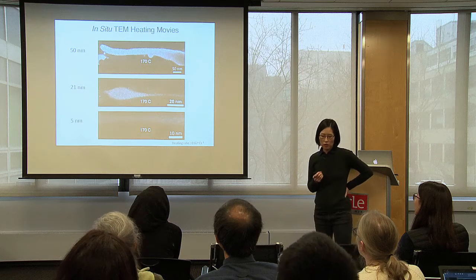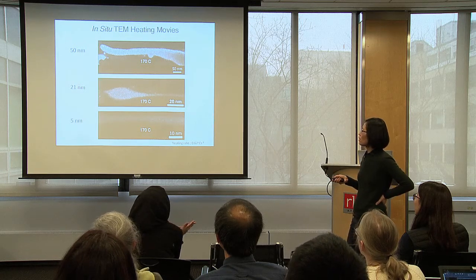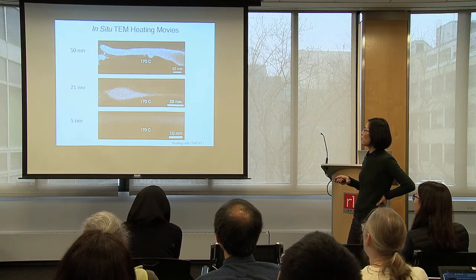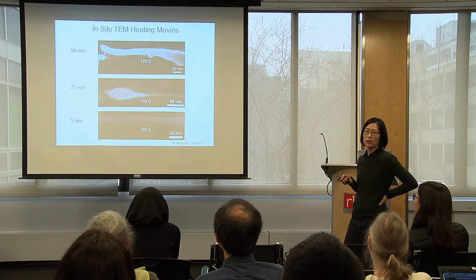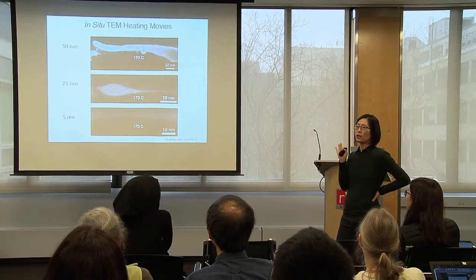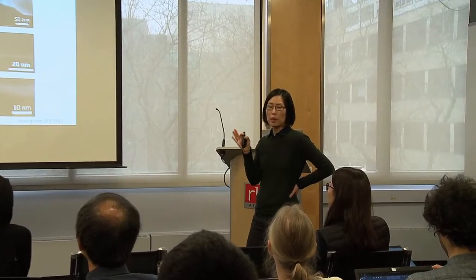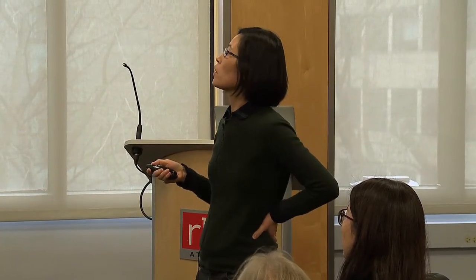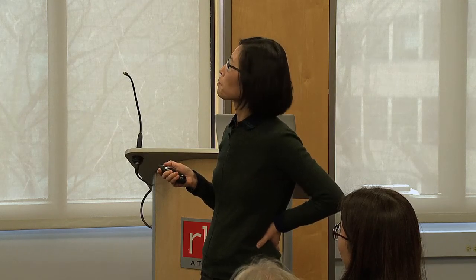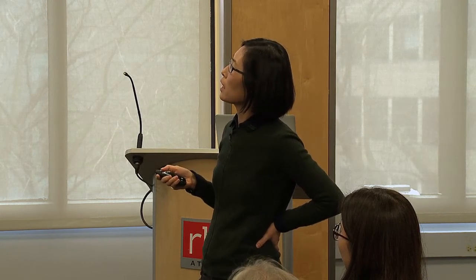So then what we did is to ramp these rods at about 2/3 degree per second from room temperature to 900, and repeat that experiment as a function of the nanorod diameter. So this is all in dark field mode. This is a 50 nanometer rod diameter. Now we're ramping. I've sped up the movie. So you see that it crystallizes at around 255 degrees Celsius.